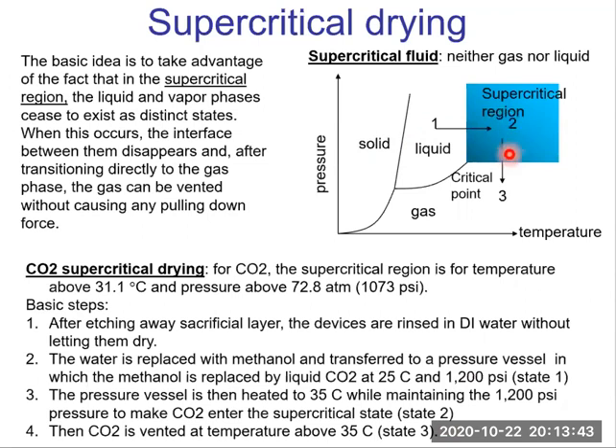Then CO2 is vented, right? We open the valve to vent the chamber so the pressure decreases at a temperature above 35 Celsius. So the temperature is maintained at 35, above the critical point, and we reduce the pressure. So now we transit from state two to state three. So the liquid CO2 becomes gas CO2 without involving an air-liquid interface. In this process, liquid and gas do not coexist.